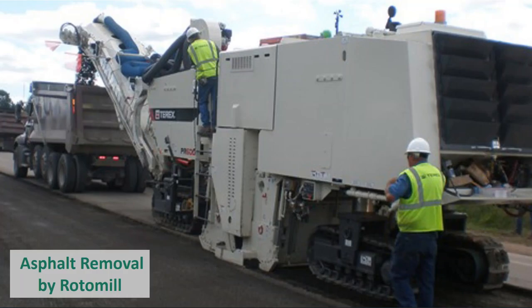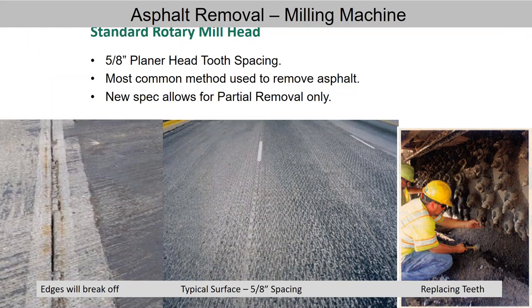So asphalt removal, this is something we didn't pay attention to quite in the past. These machines don't have a very good tolerance. They're designed for removing asphalt on roadways. We did it on bridges. And what would happen is they would remove the asphalt and then get down into the concrete deck and cause damage to the concrete decks.